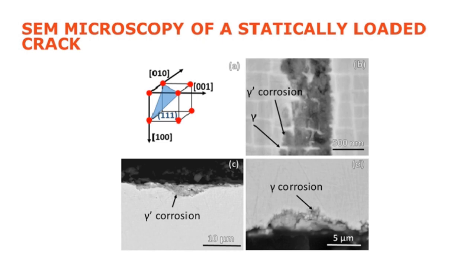So that's a corrosion pit, but it was taken on a compression side. But we can actually see that in that case, the corrosion is interacting more with the gamma matrix, potentially suggesting that there's some stress factors in this preferential attack, but also just highlighting the complexity of this corrosion mechanism as well. And certainly that echoes a lot of what I've seen. You can convince yourself of one thing, and then several weeks later you see something that's just completely the opposite. Really throws a spanner in the works.